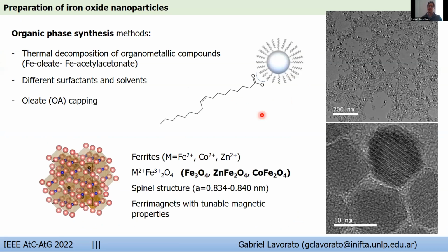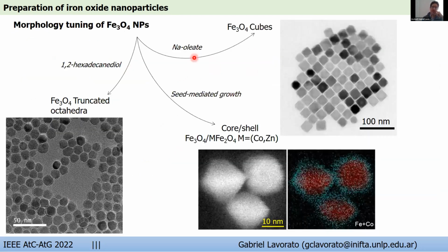Okay, so in our lab, we prepare different iron oxides by means of organic phase methods, based on the thermal decomposition of organometallic precursors by using different surfactants or solvents. Typically, we obtain oleate capped particles with very good crystallinity and a homogeneous size and shape, as shown here. This method allows us to prepare ferrites which crystallize in a spinel structure and are typically ferrimagnets with tunable magnetic properties according to their composition and size. Just to give you a few examples, by modifying the nature and the amount of the reagents in the synthesis process, we can prepare particles with different shapes, including octahedra, but also cubes or core shell particles with different size and compositions.